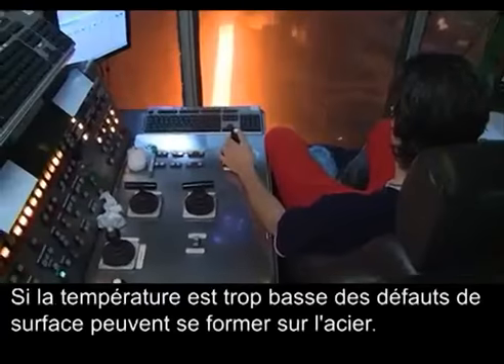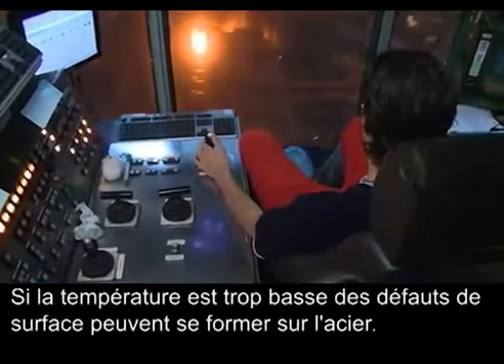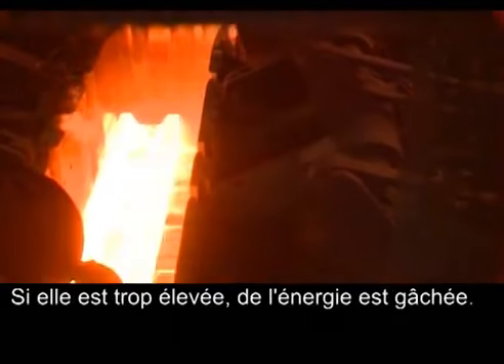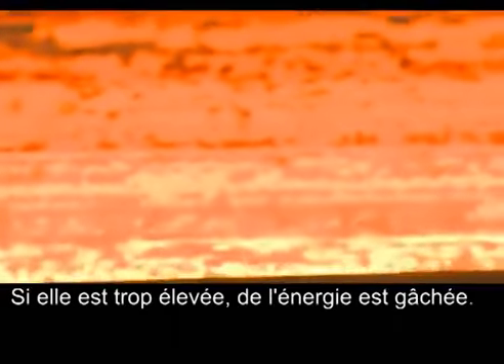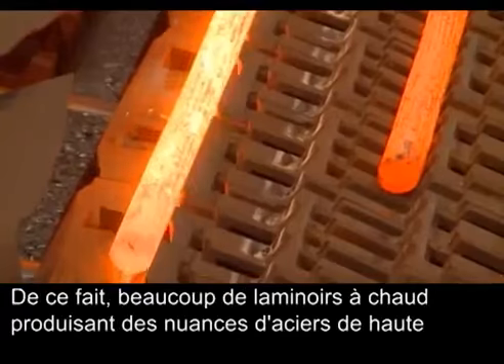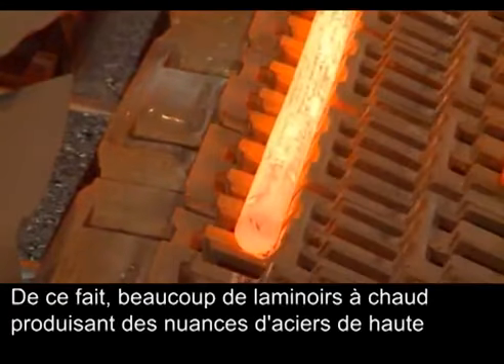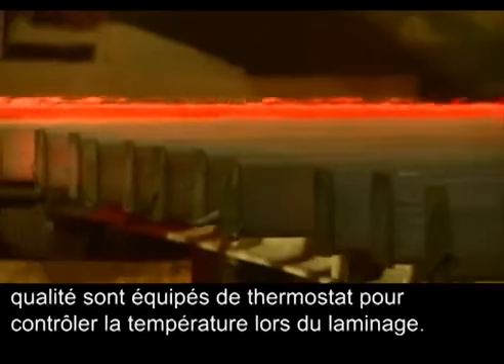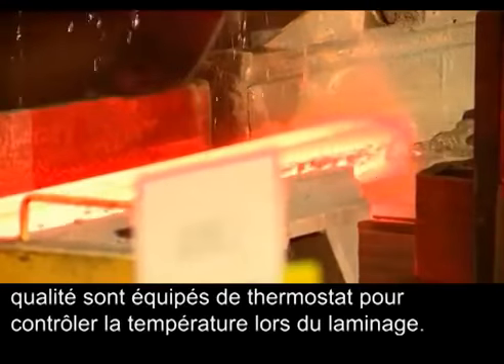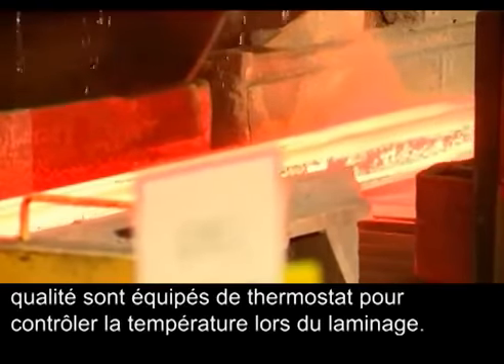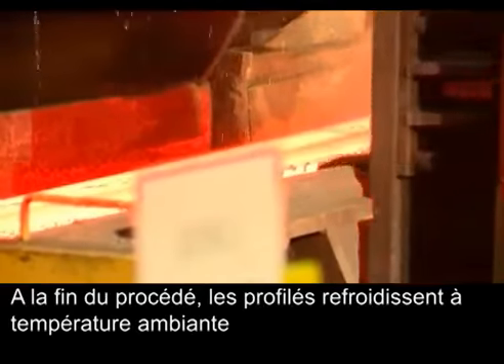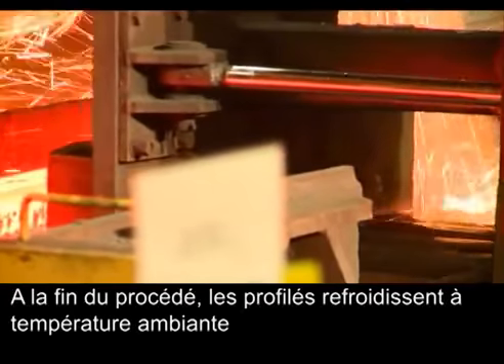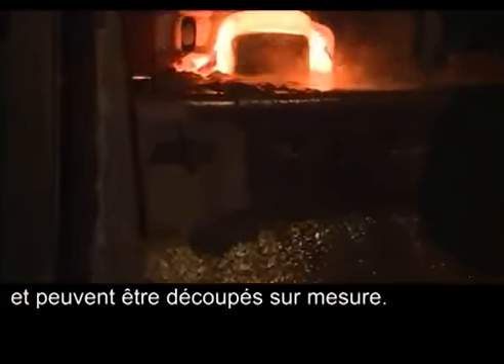If the temperature is too low, surface defects can form on the steel. If the temperature is too high, energy is wasted. Therefore, many rolling mills producing high-quality grades are equipped with devices to control the temperature during the rolling process. At the end of the process, the bars cool down to ambient temperature and can be cut to size.